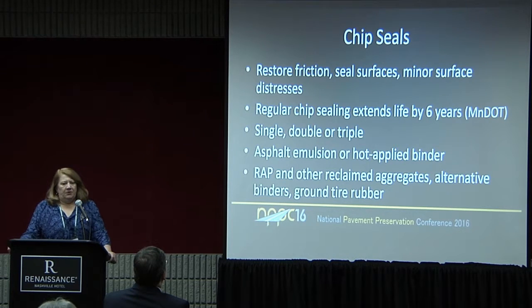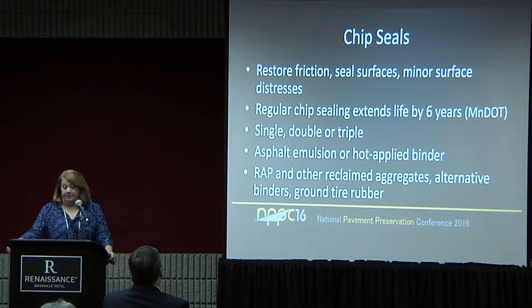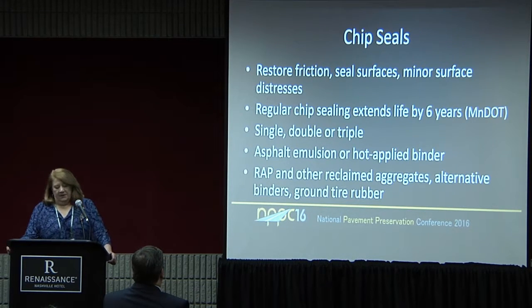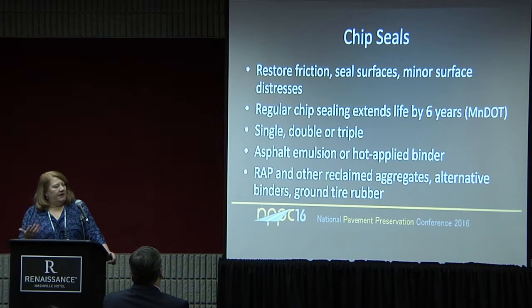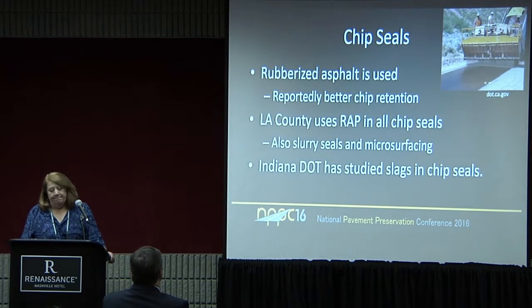So chip seals have been around for a long, long time. They can be used to seal the surfaces, restore the friction, and address some minor surface distresses. A study by the Minnesota DOT showed that regular chip sealing can extend the life of a pavement by 6 years. Since this treatment involves both an asphalt binder of some sort, an emulsion or a hot applied binder, and aggregates, it opens the door to a number of different sustainable materials that could be used. Reclaimed aggregates, RAP, alternative binders, and ground tire rubber are some of the first things that come to mind.